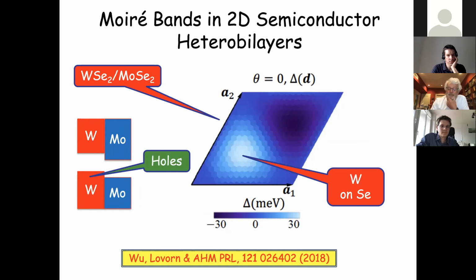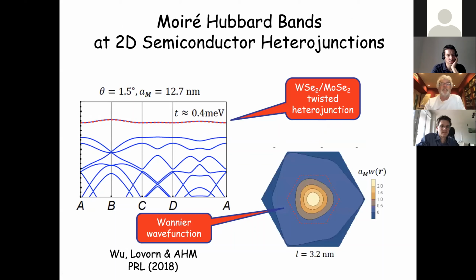And if you assume this potential is smoothly periodic, in other words, you can use the lowest shell of reciprocal lattice vectors for an expansion, then it can be expressed in terms of, in this case, just two parameters. And so you can have a simple phenomenological model with fixed modulation strength, but tunable via twist angle modulation period.